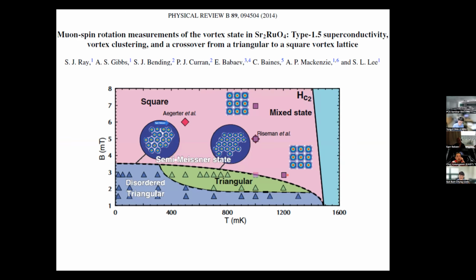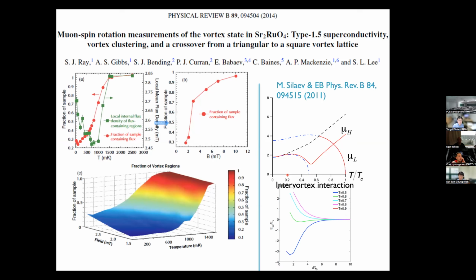But the main evidence comes in 2014, where the measurement was done with muons, and they observed phase separation into vortex clusters and normal domains. But most importantly, I'm running out of time, so I will not cover all the data, but will highlight the most important thing. If you cool strontium ruthenate in an external field and analyze with muons the fraction of the sample containing magnetic flux, then if you cool down below TC, you see first of all phase separation.